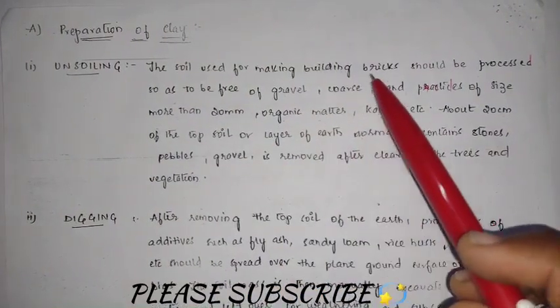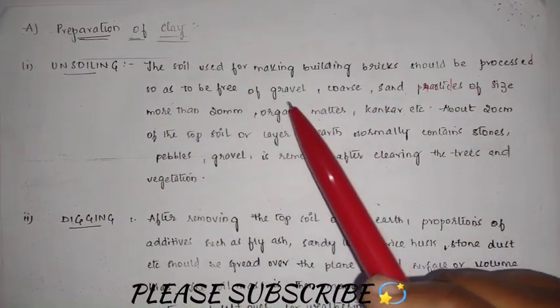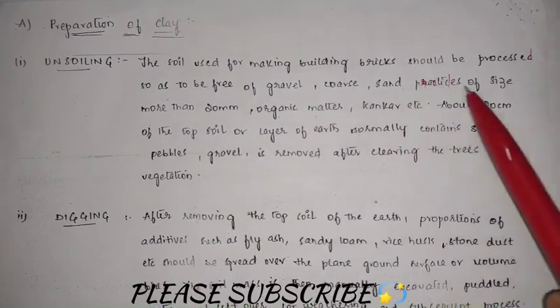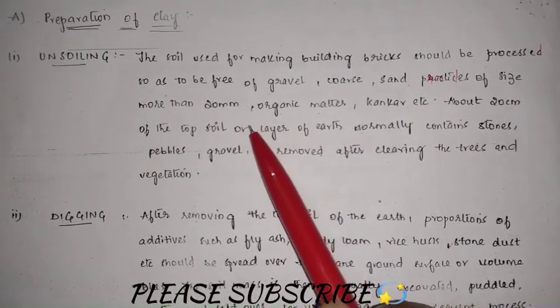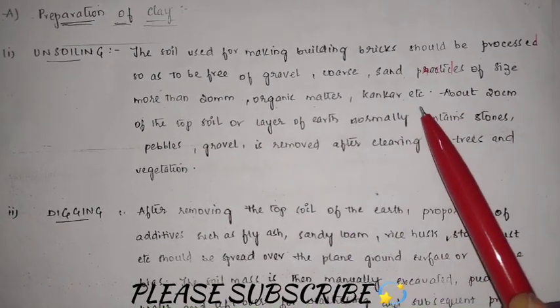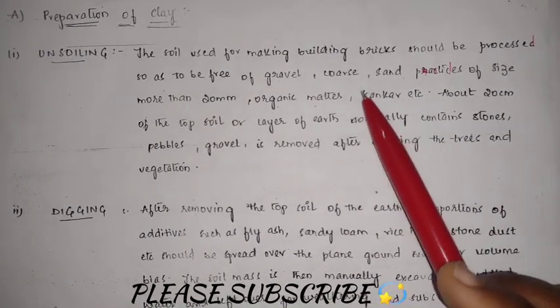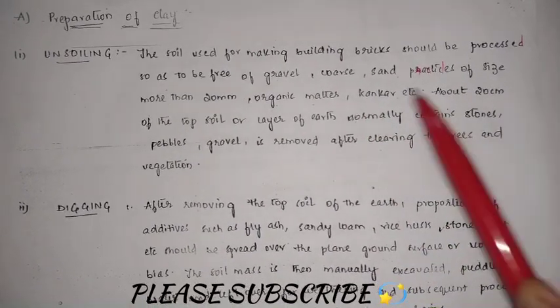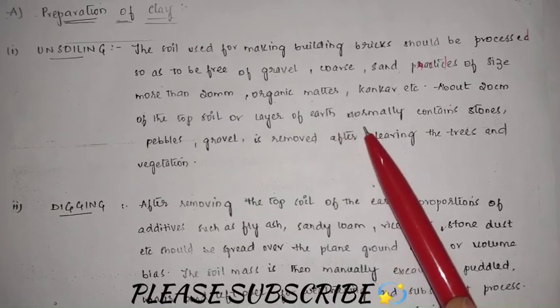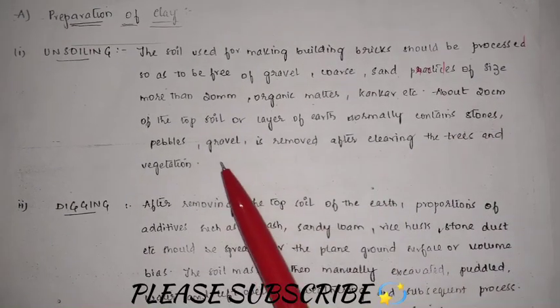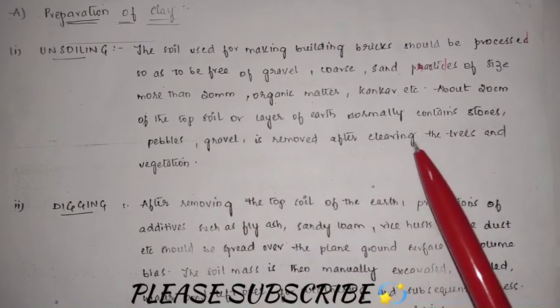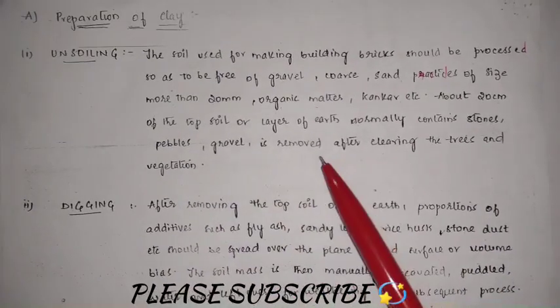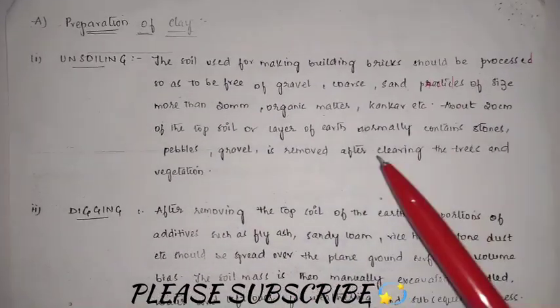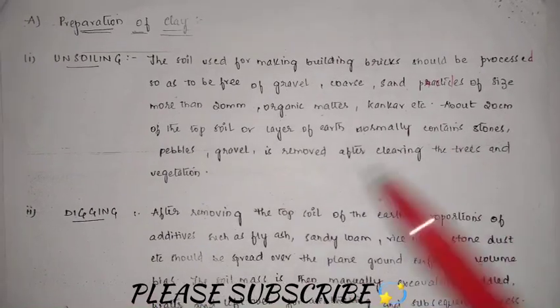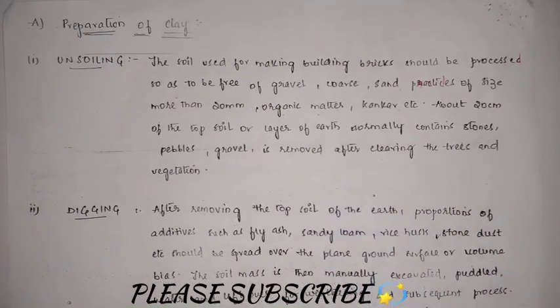The soil used for making building bricks should be processed so as to be free from gravel, coarse sand, particles of size more than 20 mm, organic matter, kankar, etc. This is nothing but coarse aggregate. About 20 centimeters of the topsoil or the layer of earth normally contains stones, pebbles, gravel, and is removed after clearing the trees and vegetations. So generally in this case we are selecting the site and we are stripping off the soil up to 200 mm in depth.